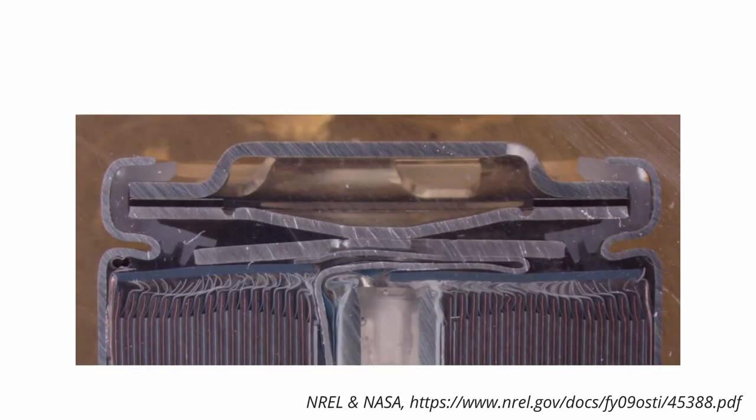This can have two effects. First, the sealing ring or gasket in the top cap can start melting. With the structural support of this insulation ring gone, the top cap and the cell housing can get into contact, causing a hard short circuit on the cell level. Another risk is that with continued heating of the PTC, the polymer with the carbon additive can ultimately ignite, leading to further heating connected with the risk of a spreading fire.